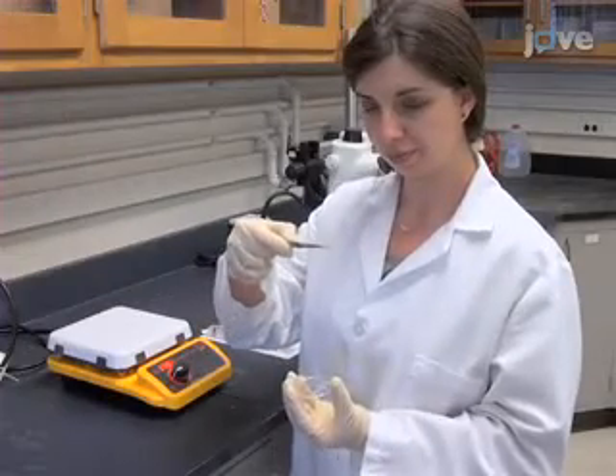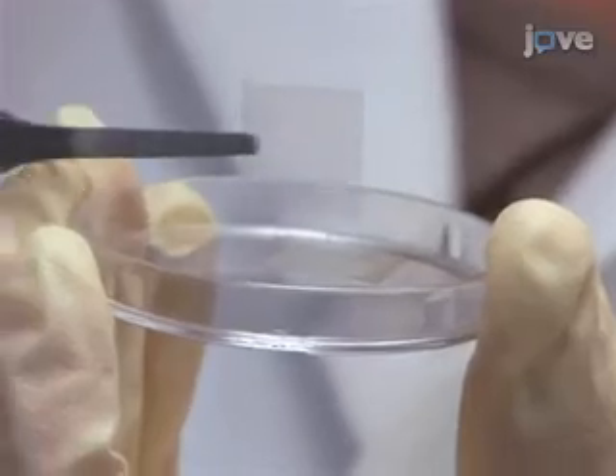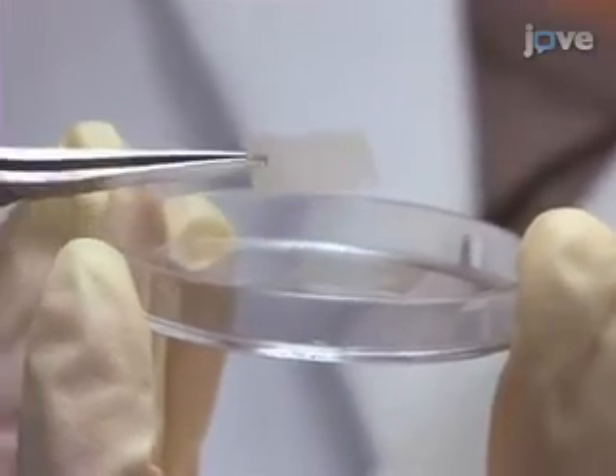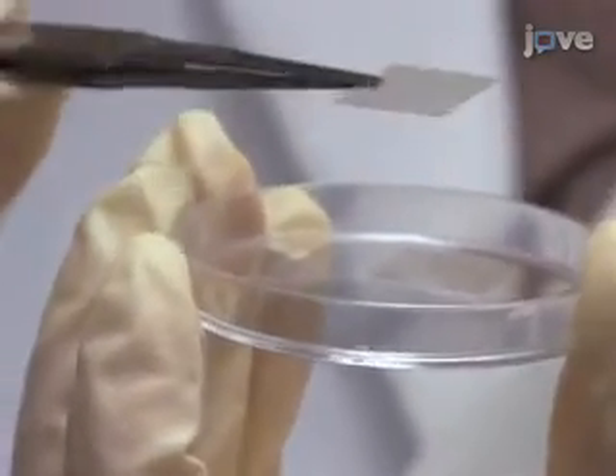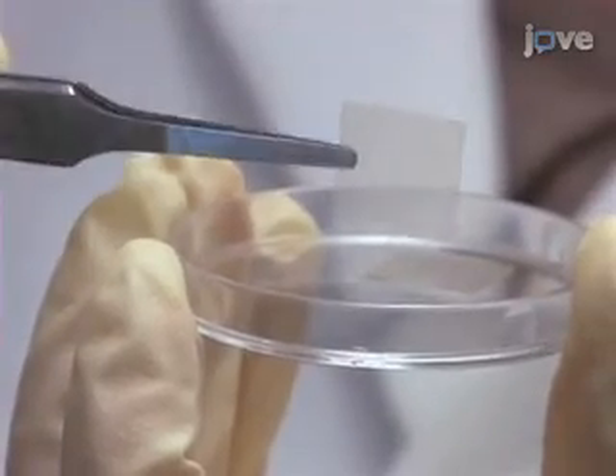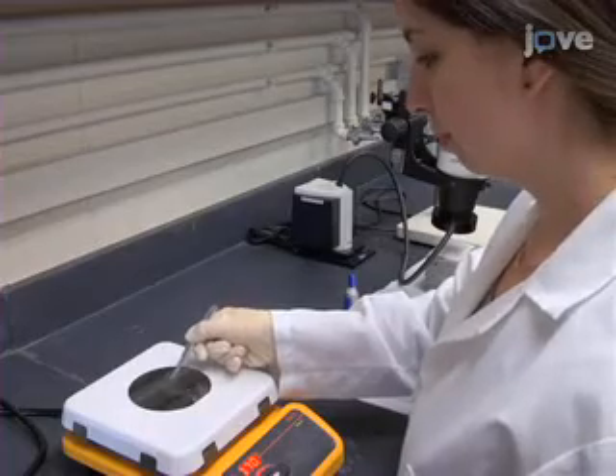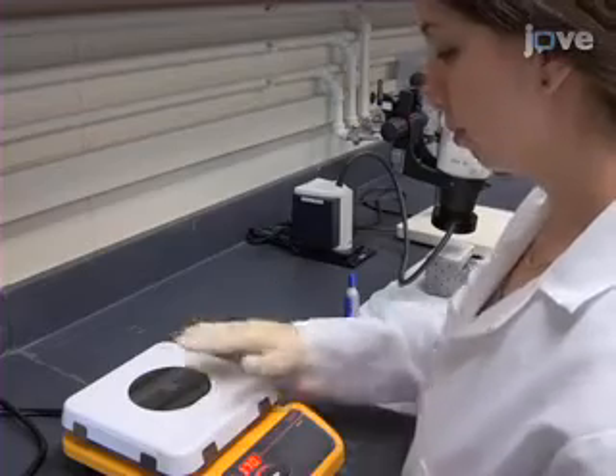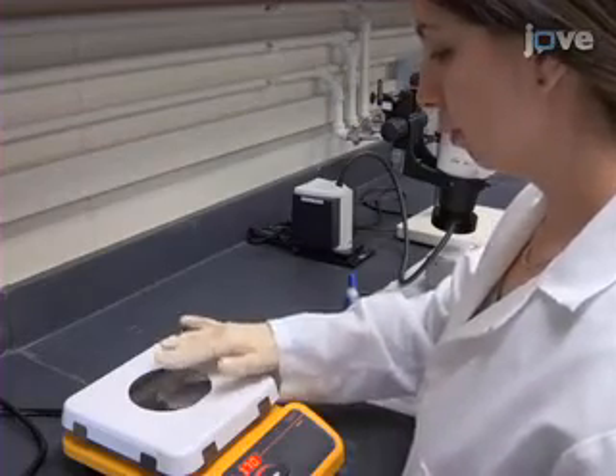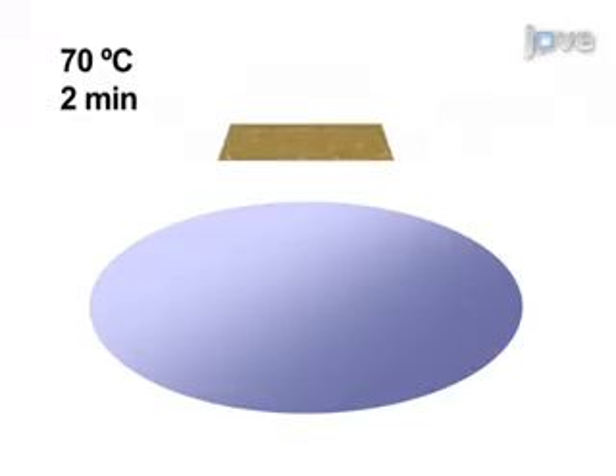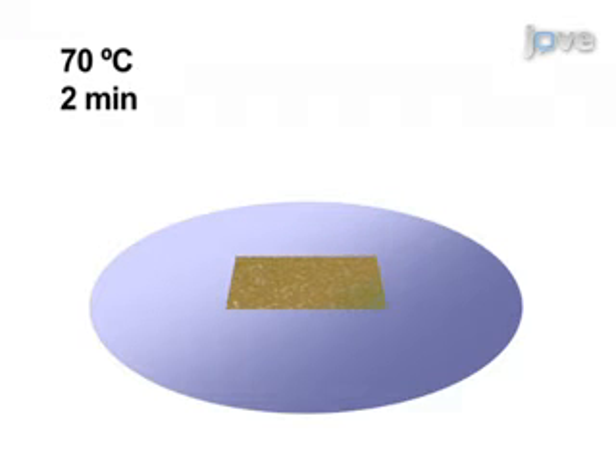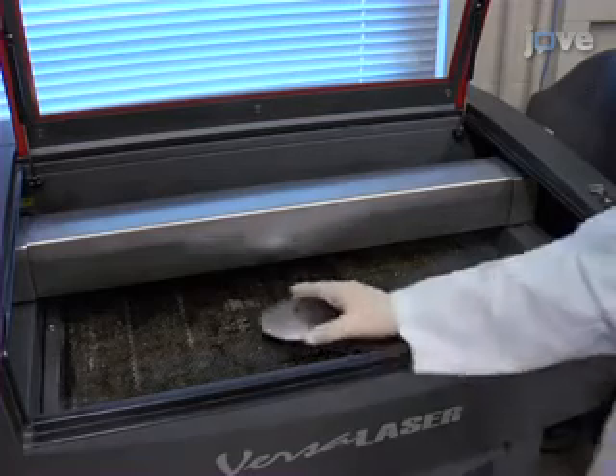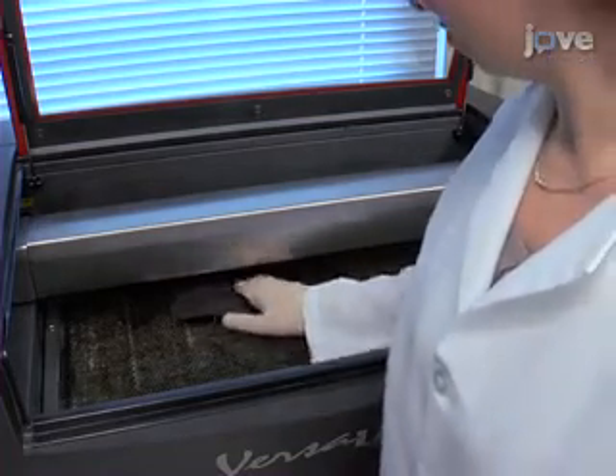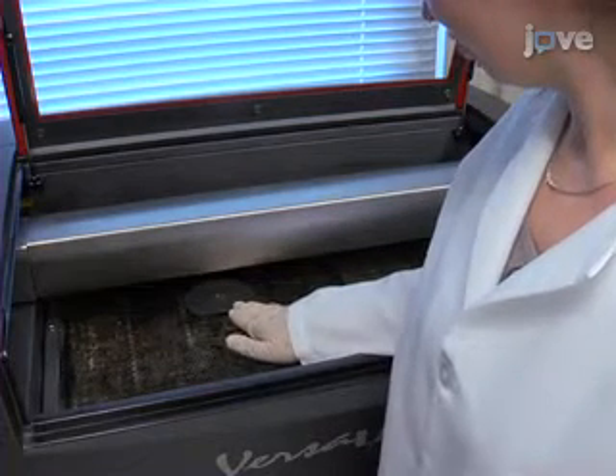First, obtain polyvinyl acetate-based nanocomposite film with a thickness of 25 to 100 micrometers produced with the solution casting and compression technique. Next, adhere the film to a silicon wafer by heating on a hot plate at 70 degrees centigrade for 2 minutes. This promotes intimate contact between the film and the wafer and ensures the film remains flat for micromachining. Now, use laser micromachining to pattern the film into the desired test sample geometries.